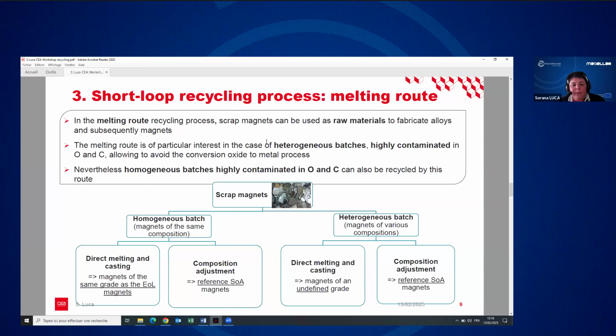This route is particularly interesting in the case of heterogeneous batches of end-of-life magnets, and especially highly contaminated in oxygen and carbon, and allows to avoid the conversion oxide to metal process. However, homogeneous batches highly contaminated in oxygen can also be recycled by this route. So this process is versatile. Two kinds of scenario can be seen and can be used for this recycling process. And I will show you later some examples of magnets recycled by these routes.